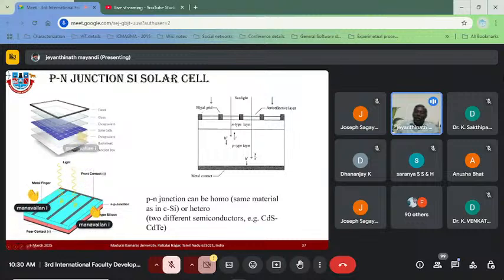And then you make metal grids with silver on top of it, and the backside is coated with aluminum. These cells are then packed in such a way that they are not destroyed or exposed to the atmosphere with dust and so forth. To do that, we have this assembly. You see the junction box here, and then a back sheet, and then an encapsulation layer of polymer on the front side and back side. The front side is optimized for photon absorption into the solar cell device. And then the glass plate and the frame.